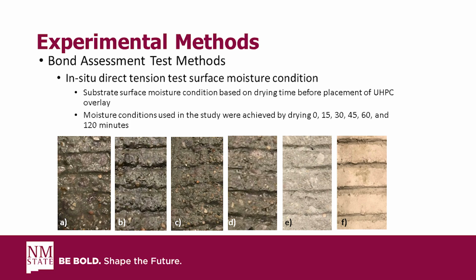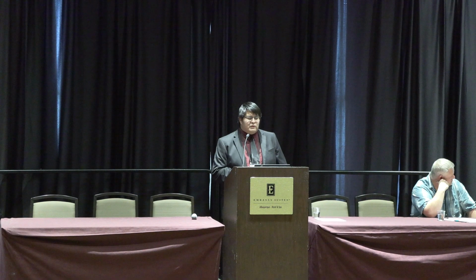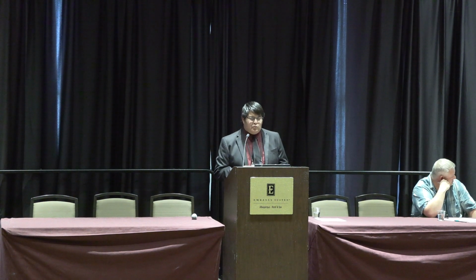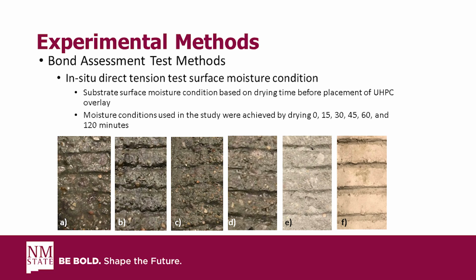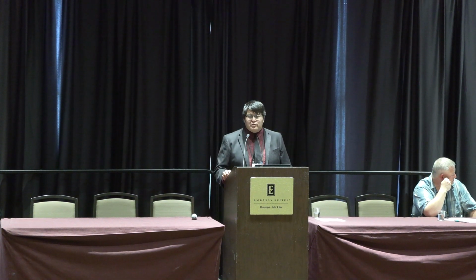And now going into the substrate surface moisture conditions. First off, we wanted to look at surface conditions from saturated all the way to dry. The image on the left here is our saturated case, so you can see some freestanding moisture and water on the surface. We call this the zero minute dry time because we maintain saturation up until application of the UHPC overlay. And then for the other moisture conditions we just allow it to dry. Of course, the time aspect is dependent on the location, and here we're looking at a laboratory which has 68 degrees Fahrenheit and 30% relative humidity. So that's just descriptive for these photographs.